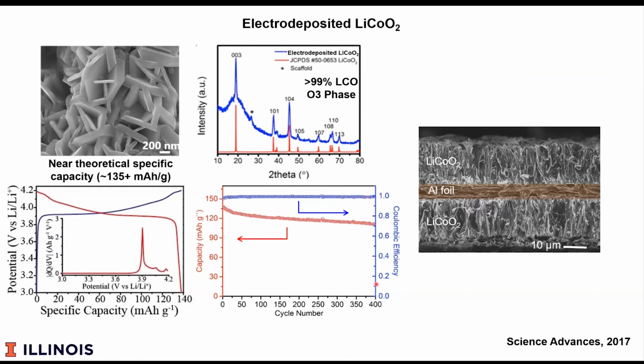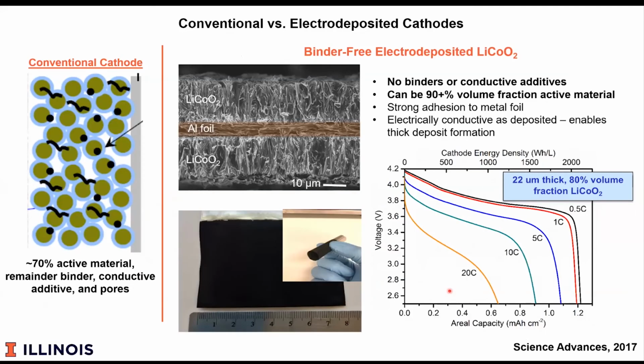If we look at this a little bit more in the details, again, a conventional cathode, say 70% active material plus binder and conductive additives. Here, the active material volume fraction is anywhere from 70 to 95%. It's robust. I mean, this is important for the engineering aspects because the batteries are made by reel-to-reel processes. And this happens to be a 22 micron thick material. And this shows that in a 12-minute charge or discharge, it has about 90% of the energy as the material would at very slow charge and discharge. And if we compare this with a commercial battery, at this sort of rate, it might have 50% of its energy. So there's a very significant advance in the charge and discharge kinetics relative to the slurry-cast systems.